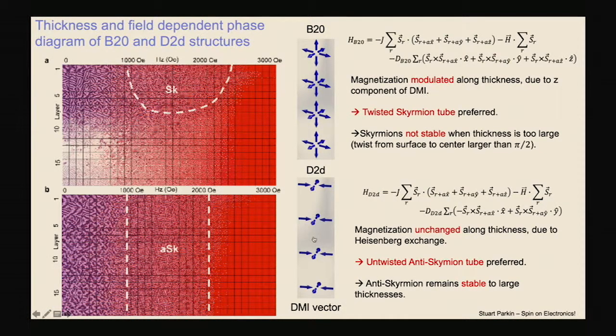And now in these simulations, of course, we include the appropriate symmetry of the Dzyaloshinskii-Moriya exchange vector. On the top, we compare the cubic B20 chiral system, and we find that as we increase the thickness, which is from top to bottom on the top left, you can see the dashed white curve shows you where we see skyrmions. And as you increase the thickness a little bit, you see they disappear. Whereas the antiskyrmion in the same simulation, you can see there's no dependence of the region where antiskyrmions are stabilized as a function of increasing thickness.